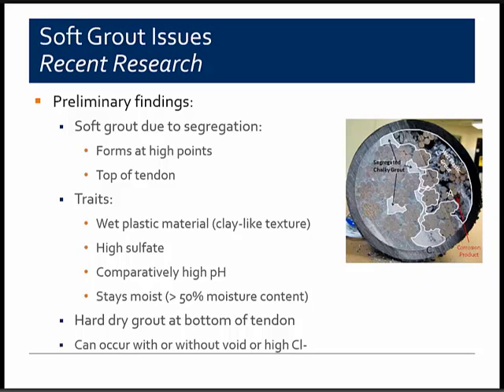In terms of the nature of the soft grout material, the research has found that it tends to occur at tendon high points on the top side of ducts as a result of segregation. Now, that's not unlike the normal segregation and bleed water problems that can manifest in PT tendons given certain conditions, particularly with traditional Portland cement grout mixtures. However, the regions of soft grout are different, and they're unlike the normal segregation and bleed water issues where the water may tend to evaporate or be reabsorbed, just leaving a grout void.